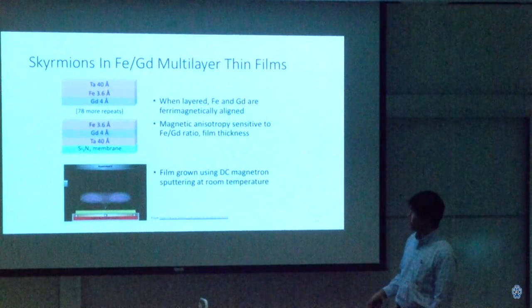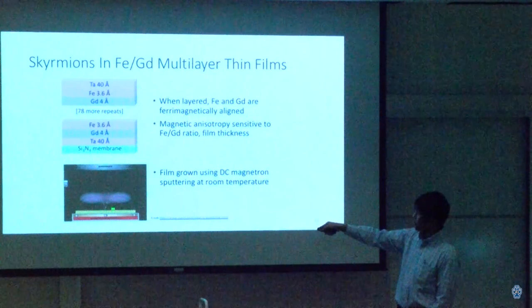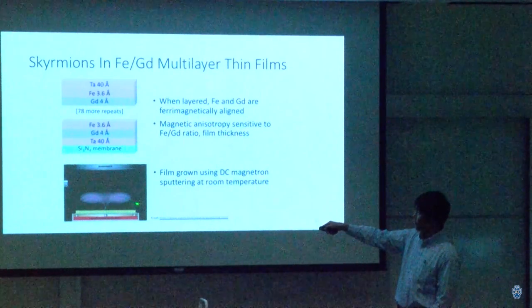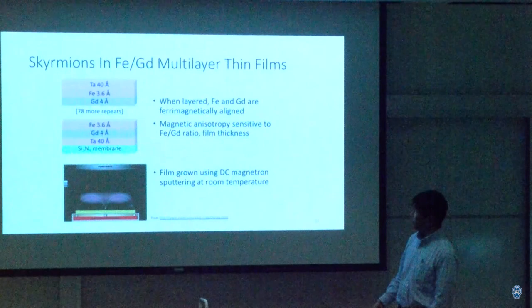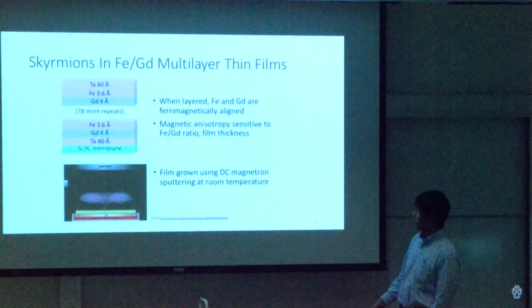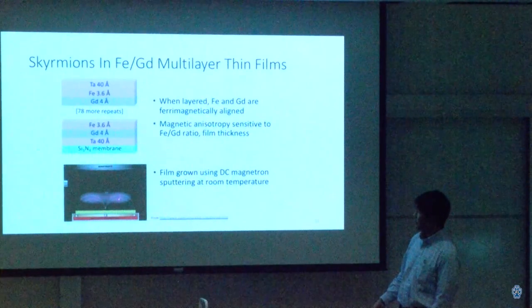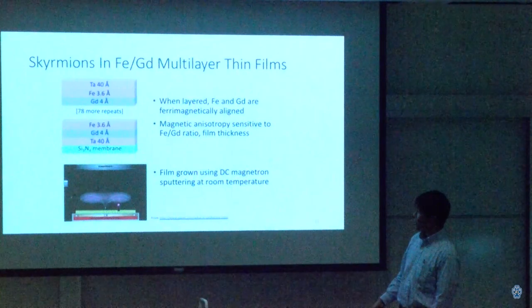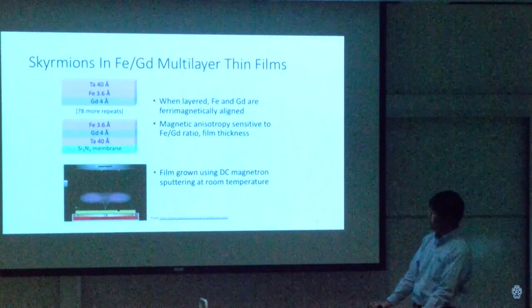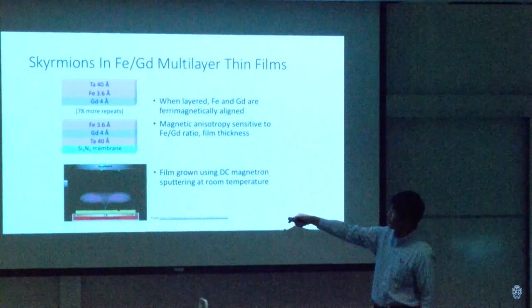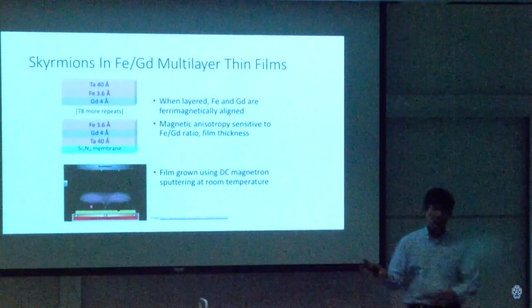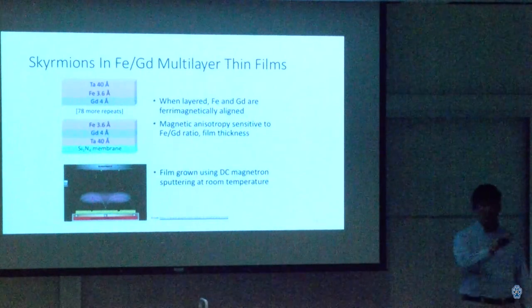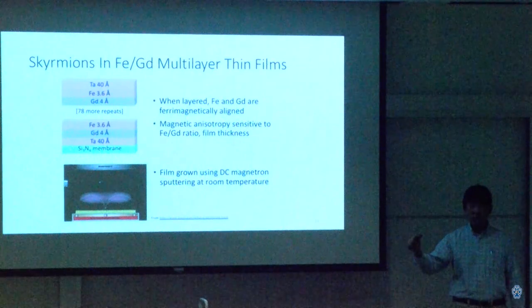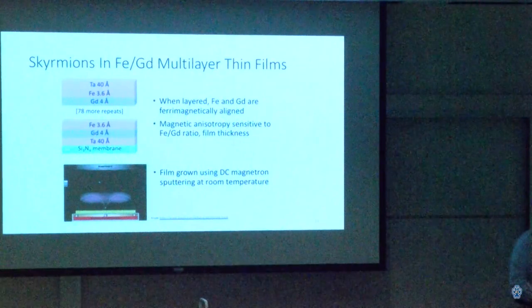So here's the animation again. The electrons trapped by the magnetic field whizzing around. Here's an unsuspecting argon atom about to be hit. Bang. You have an ionized argon ion being dragged down to the target, and you saw some target atoms make it to the substrate. You do that often enough, you can create a monolayer of some material. You do that over and over, you get the sample.